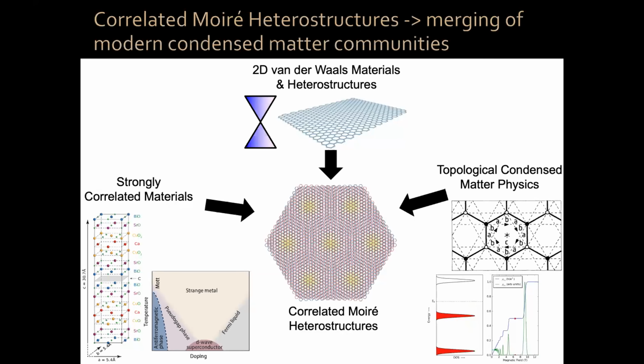I'm not aware yet of a lot of reports where the spin-orbit coupling itself has been identified as having done something. There's an interesting paper by the group of Stevan Nadj-Perge at Caltech, where he put magic angle graphene on WSe2, and he saw that these effects of correlated insulators and superconductivity seem to change. So that might be due to spin-orbit coupling, or it might be due to screening due to the high dielectric constant of the system. It's not entirely known yet. So they're having effects, but I don't think people have seen direct effect of spin-orbit coupling in magic angle graphene yet. I see. Thank you so much. All right. Please join me in thanking Pablo again for this magnificent talk.